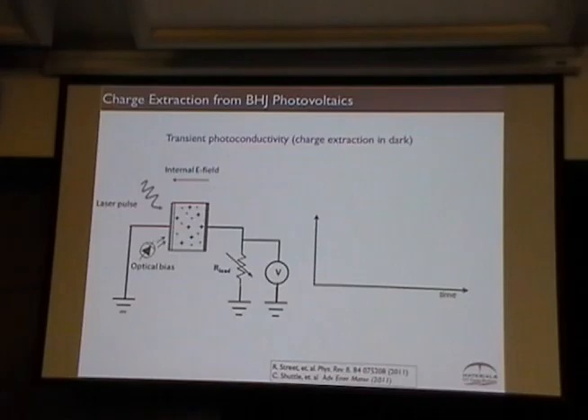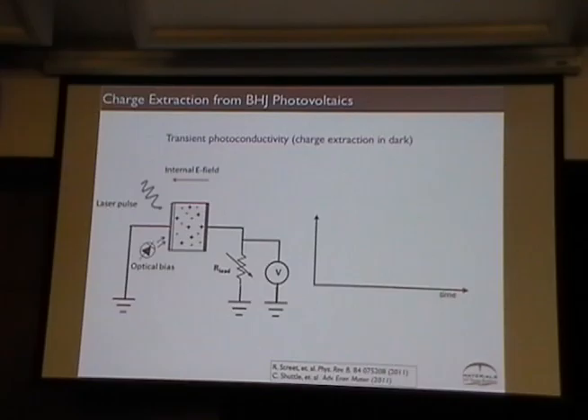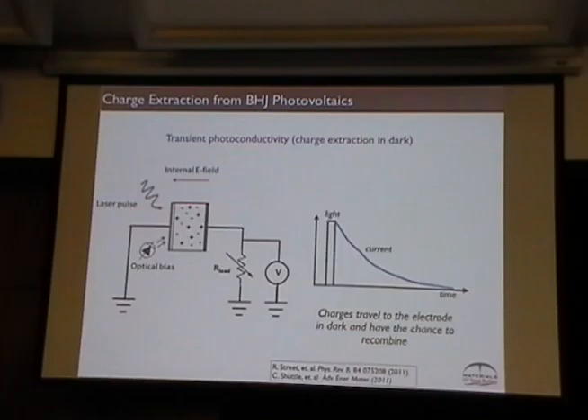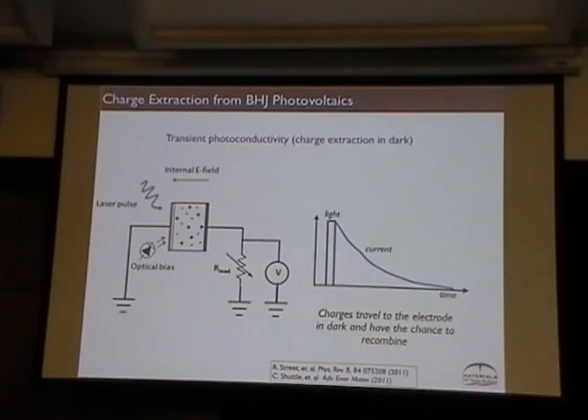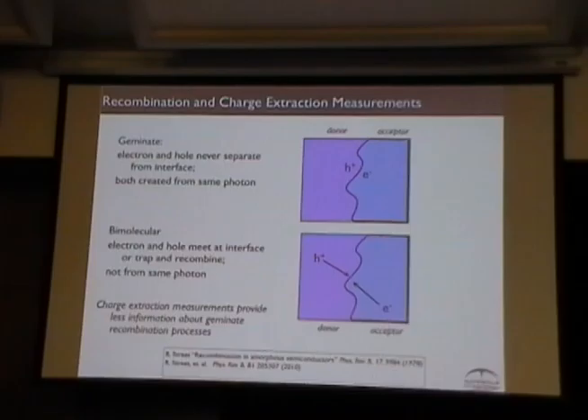If I do something like a time-of-flight experiment — we'll call it transient photoconductivity, or charge extraction — I take my solar cell, apply a bias, have a resistor, and measure a voltage at that resistor. I send in a pulse of light, turn it off, and measure the current that flows — it's just going to decay. During the decay, the hole and the electron could recombine. This is unlike the time of flight; you apply some voltage and maybe send in dilute charge to try not to perturb the voltage. The current will decay much like a time-of-flight signal.